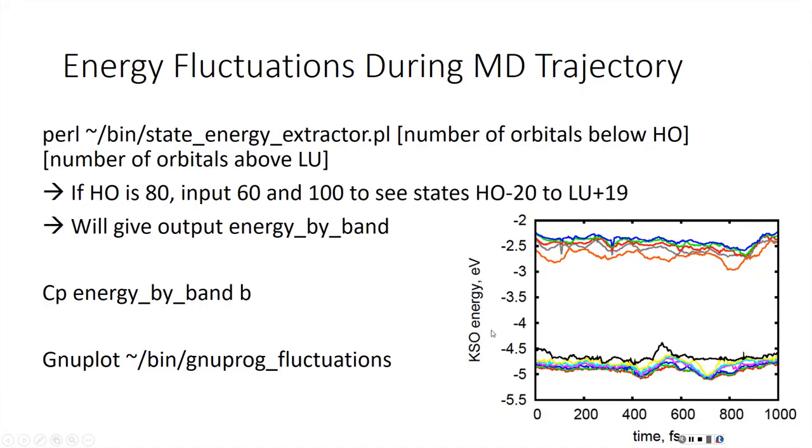So what is the feature you mean by abnormality? So like if an atom broke off, like a fragment broke off during the MD trajectory, you should be able to see changes in the energy fluctuations because your electronic structure is going to change dramatically. Because I know like John, in his last perovskite project, he had formations of iodines during the trajectory. There was a line that went way up into the middle. So that gives you an idea of whether there's some sort of chemical dynamics occurring during the trajectory.